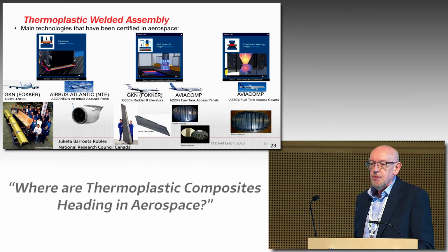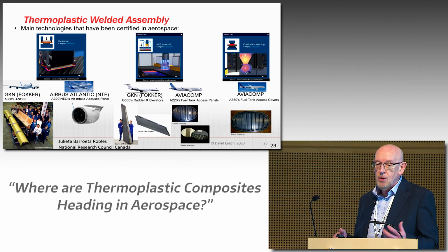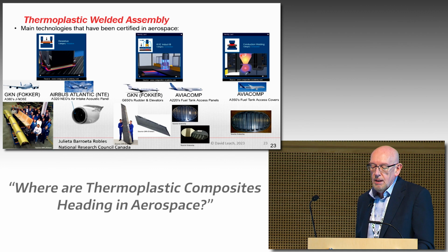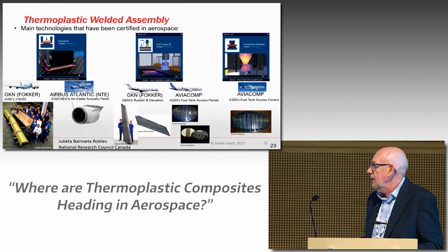Welded assembly, there's various techniques already available for welding that have been proven, certainly on the smaller scale, even at production levels, with resistive welding, induction welding. A lot of the induction has been done with fabrics because you typically don't want to use a susceptor in there, which puts a defect into the weld zone. And in terms of inducing the current and therefore the resistive heating in the weld, fabrics, of course, lend themselves much more because you get the induction loop created. Unidirectional materials is more of a challenge, and there's quite a lot of R&D work going on right now to really be able to characterize that and focus the heat into just that area of the weld.